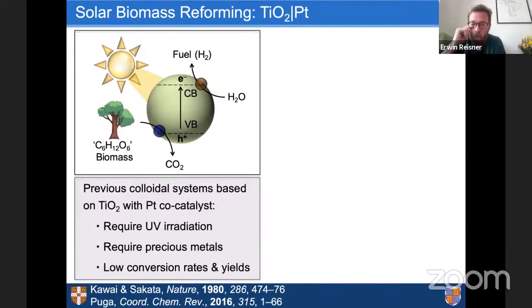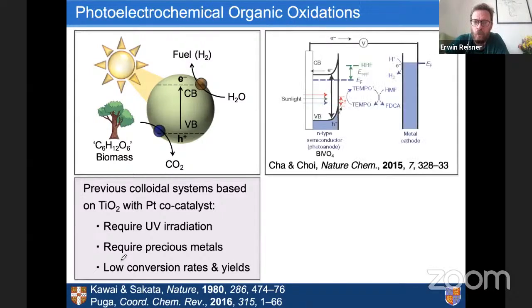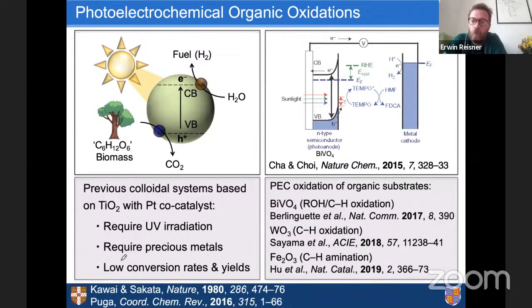All systems studied before relied on titanium dioxide as the light absorber and platinum, or at least a precious metal co-catalyst. If you use this combination, then you have quite some drawbacks. One is that titanium dioxide, as a wide band gap semiconductor, requires UV light, so it will not efficiently use sunlight. Of course, the use of precious metals is expensive, and overall the yields and rates were quite modest. So I think the proof of principle was established, but with several drawbacks. I would just like to mention also some newer work on the photoelectrochemical oxidation.